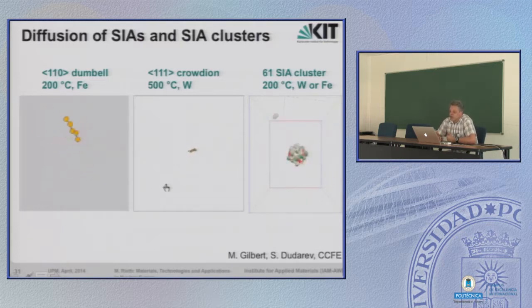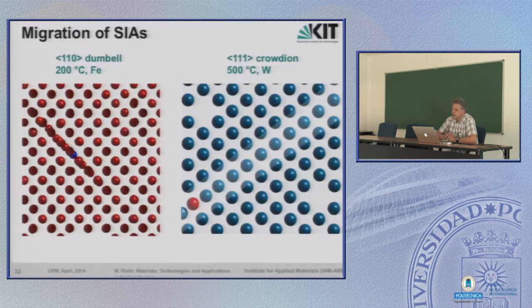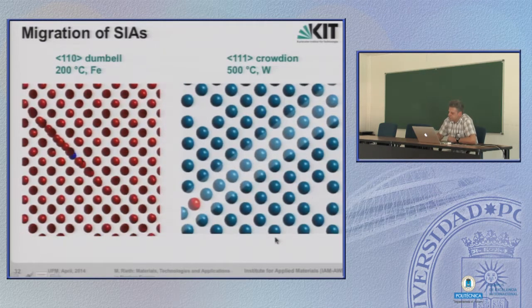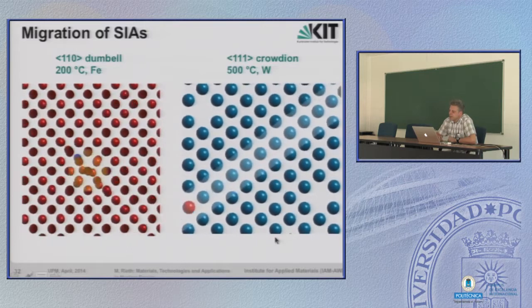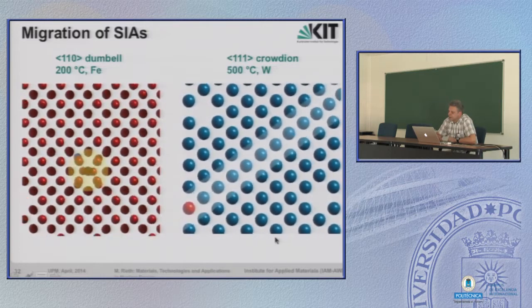Okay, this is for iron, this is for tungsten, because in tungsten the crowdion is stable, and self-interstitial clusters can be in tungsten or iron. This doesn't make any difference. What I want to show you here is that these defects and defect clusters are moving inside the lattice. Here is another example. Here, this is how the crowdion is moving.